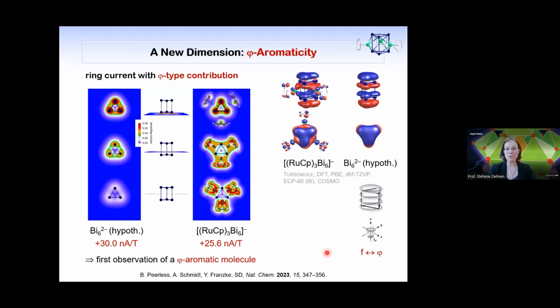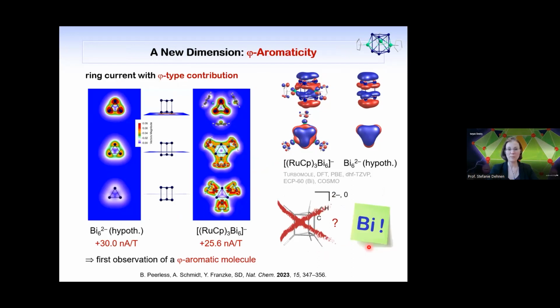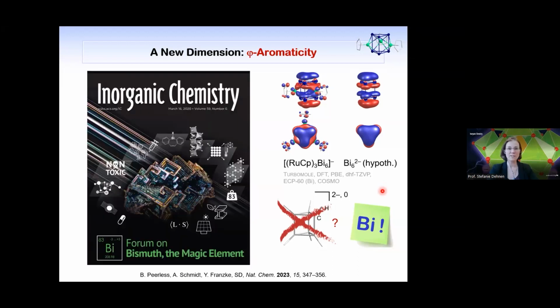We also tried and calculated this for an organic counterpart, so prismane or prismane anion, and we found out very quickly that this does not work. This is not an aromatic molecule. You have no phi aromaticity here. So we need the metal, we need bismuth for it, and this was rather unexpected, that bismuth would be a better aromat than something that is organic. And for this, it's easy to refer to a nice forum issue that we had on bismuth, the magic element. It can do pretty much everything you would like to have.